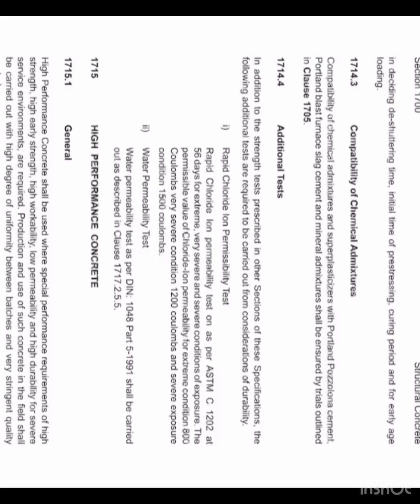Additional tests. In addition to the strength test prescribed in other sections of the specification, the following additional tests are required to be carried out from consideration of durability. Rapid chloride ion permeability test as per ASTM C1202 at 56 days for extreme, very severe and severe conditions of exposure. The permissible value of chloride ion permeability for extreme condition is 800 coulombs, very severe condition 1200 coulombs and severe exposure condition 1500 coulombs.